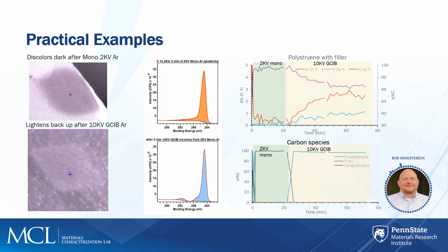But more importantly, we start seeing coming out of the material titanium and oxygen. And that's actually from the material. If we just make a plot of just the carbon species, whether it be an amorphous versus what we expect for polystyrene, you can actually see a transition of that in the lower slide. So not only was I able to make this material recover by going to the 10 kV, but I was able to keep the chemistry.